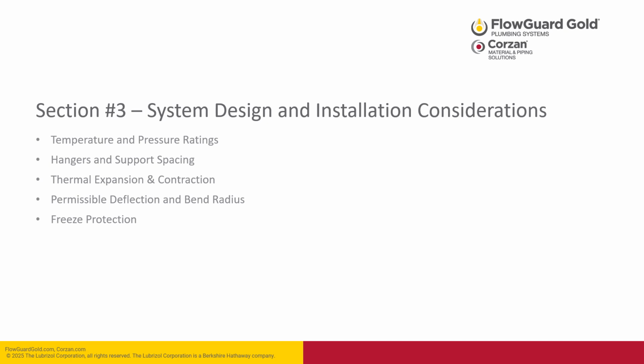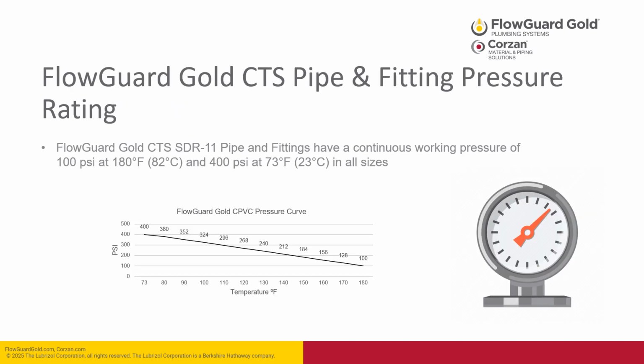Now let's talk about some common system design and installation considerations, ranging from temperature and pressure ratings, hangers and supports, thermal expansion and contraction, deflection, and freeze protection. FlowGuard Gold copper tube size pipe and fittings are an SDR11 system, meaning that they have a continuous working pressure across all sizes. For FlowGuard Gold, that is 100 psi at 180 degrees Fahrenheit and 400 psi at 73 degrees Fahrenheit. You can see in the chart below the linear relationship. As temperature increases, the pressure rating will decrease.